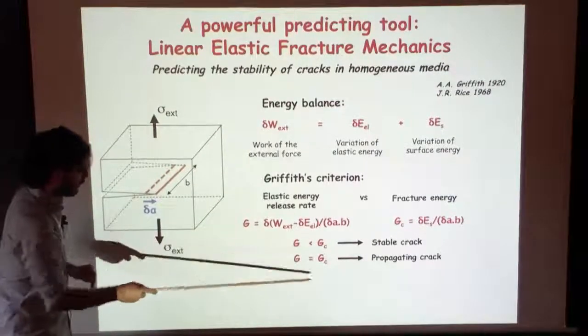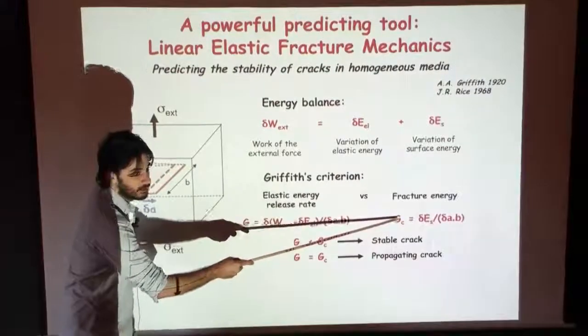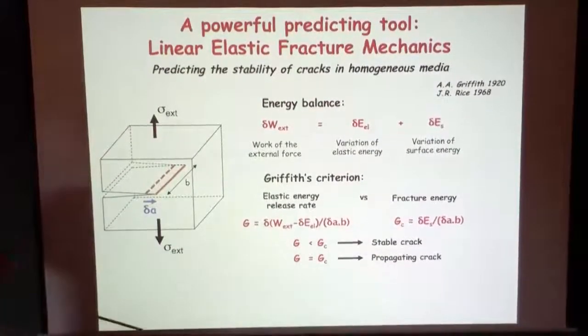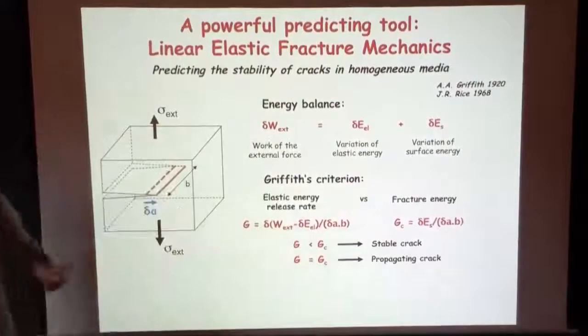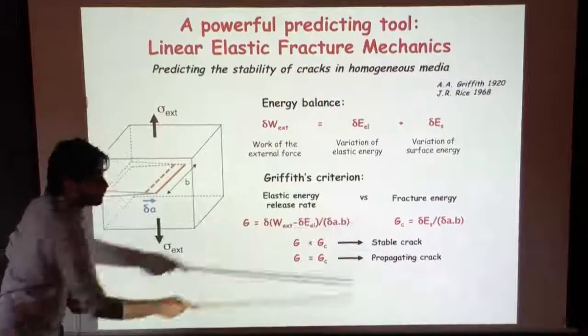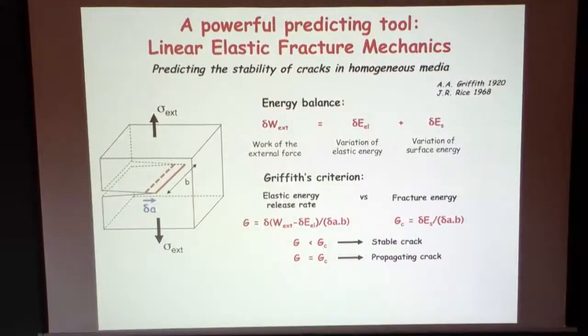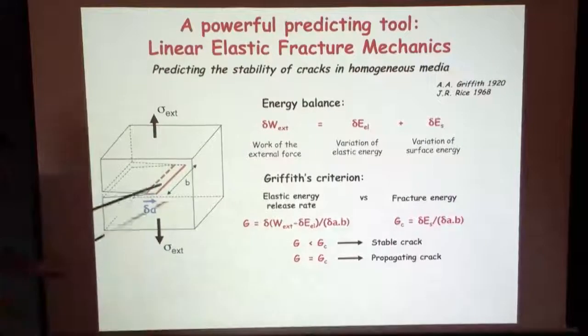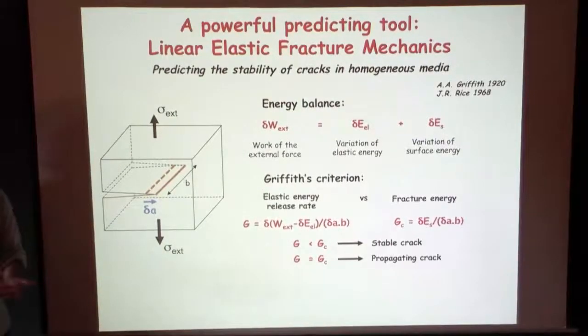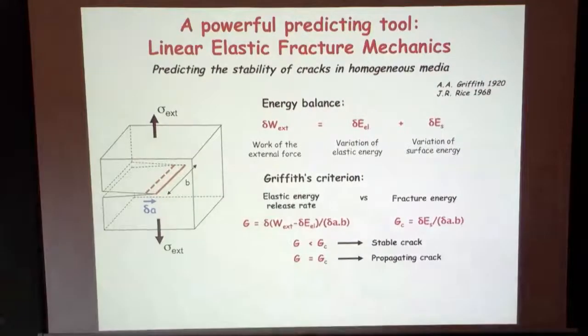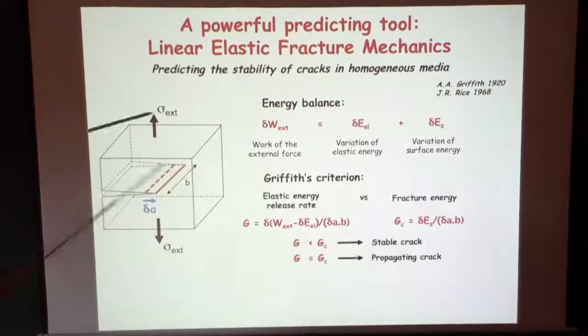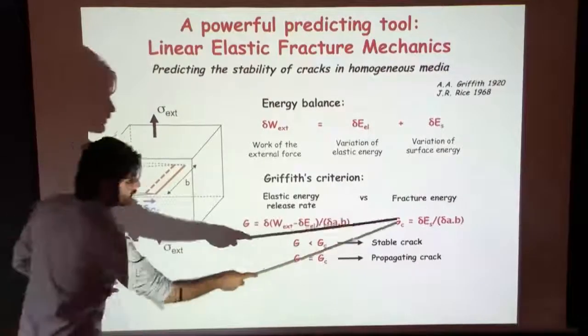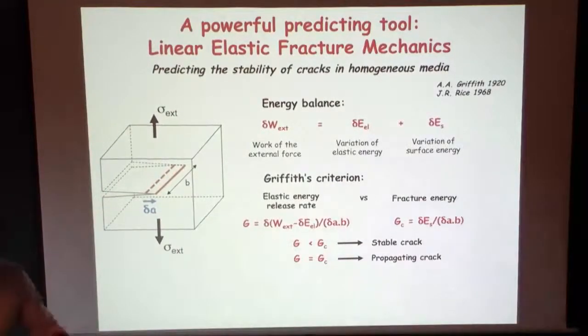So we have put all our trouble in this term, and as you do in fracture problems, you're going to open the box each time. What is inside this term? What do you call dissipation? Practically speaking, we can measure it on different materials and have tables of fracture energy values, but there's no explanation from this type of continuum mechanics approach. You cannot have any insight on the value of GC. And you assume that it's a constant that depends only on the surface that is broken.